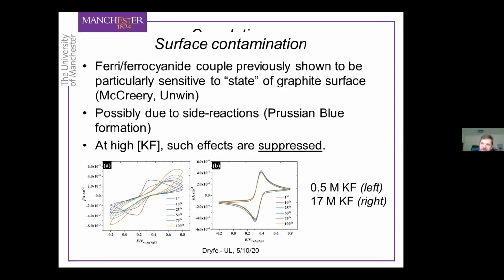Whereas if we do the same thing, same ferricyanide redox couple, but instead of using a more classical electrolyte concentration of 0.5 molar, we work at 17 molar, you can see that not only is the CV much more reversible, as I've already talked about, but it's entirely reproducible. Even the 100th scan more or less completely overlays the first scan. So all these contamination effects, whether they're from the molecule itself or from contaminants from the atmosphere diffusing through the aqueous solution, they are completely suppressed by going to these very high electrolyte concentrations. So you've changed completely the nature, the structure of the electrode-electrolyte interface at these very high electrolyte concentrations.